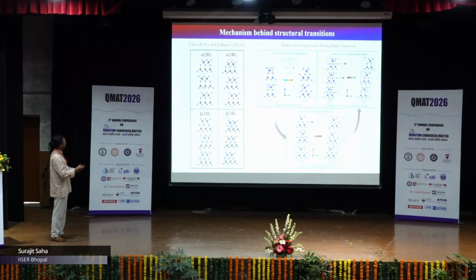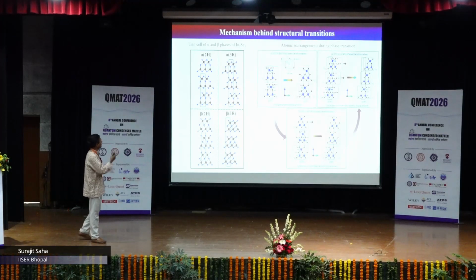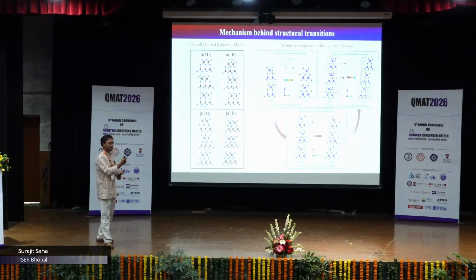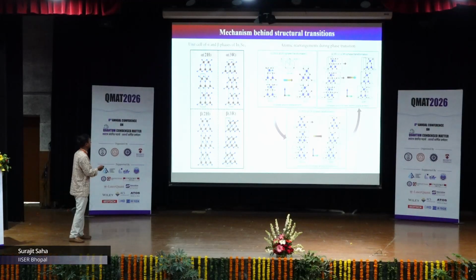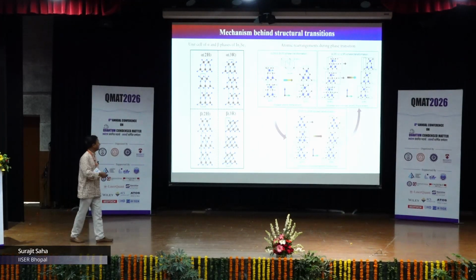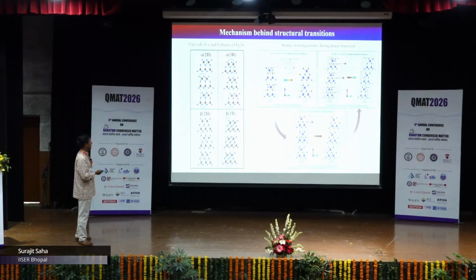Now, the mechanism that we are putting forward is how the structural transition happens, basically the rearrangement of the atoms. You can see this is the tetrahedral coordination. These upper layer atoms in the quintuple layer move by about 1/3 of the unit cell to form the new structure. That's how it goes from alpha 2H to beta 2H, and then eventually from beta 2H to beta 3R, and then comes back to the 3R phase.